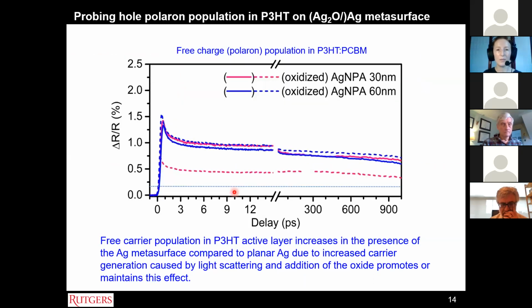And he did some transient absorption measurements, and he showed that the addition of the oxide was very good for photovoltaics, for maintaining a high polaron population in P3HT. You can see here for the 30 nanometer particles, the oxidized compared to the unoxidized case, there's an increase in the polaron population, to an extent that it's almost as good as that of the 60 nanometer particles, which increase the polaron population by increased light scattering. So addition of the oxide promotes or maintains the large presence of free carriers, positive free carriers, in the P3HT, which aids in increasing the photocurrent.